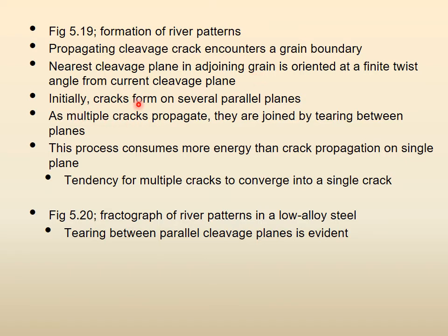Initially, cracks form on several parallel planes. As multiple cracks propagate, they are joined by tearing between the planes. This process consumes more energy than crack propagation on a single plane, right? On each plane, crack is propagating and that needs some energy. But when there is a tearing between the planes, then there is more energy. So there is tendency for multiple cracks to converge into a single crack.